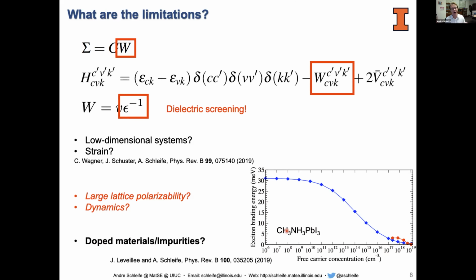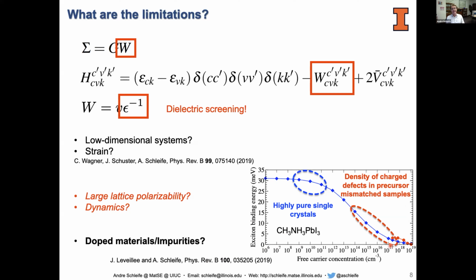And in that material, I will just come back to the bottom line. Josh published more details in this paper. But if you're looking at highly pure crystals of this material, in other words, very low unintentional doping concentrations, exciton binding energies would be higher. That's what the numbers here come from, our predictions. If you look at maybe precursor mismatch samples that are also reported in the literature, maybe there are more defects present. So in other words, there is unintentional doping and you see lower binding energies. And indeed, if you look at the literature, you do see that the range of binding energies reported for this material is large. And we believe that effects because of this, and the corresponding unintentional doping, can at least explain this behavior in part.